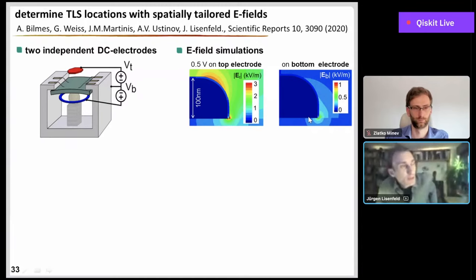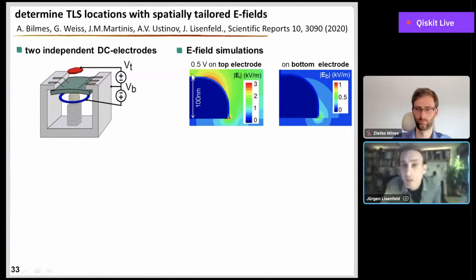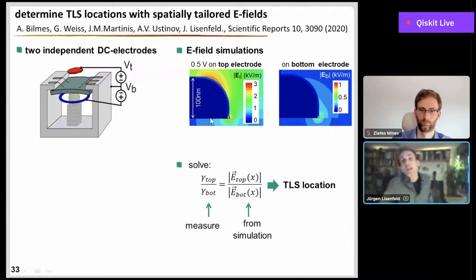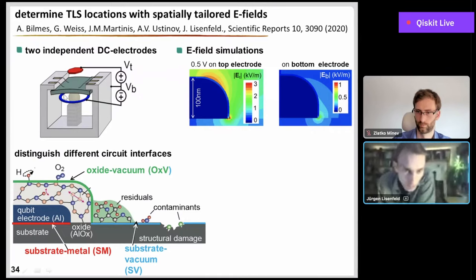And the idea was that we could actually use this to determine the location of the defect along this electrode. So we would like to say whether it's here or there, for example. And we can do this simply by measuring the response or the coupling of each defect, both to the top electrode and to the bottom electrode. So we measure this ratio here, and then we look into our simulation to find a similar electric field ratio, at which position we find this ratio of the electric fields. And then we have basically a possible solution for the position of this defect. And by this, we are now actually able to distinguish whether these defects on the surface electrodes, on the surfaces, are residing here on the very surface of this oxide layer, inside this oxide layer, or whether they, for example, are buried under this qubit electrode here.